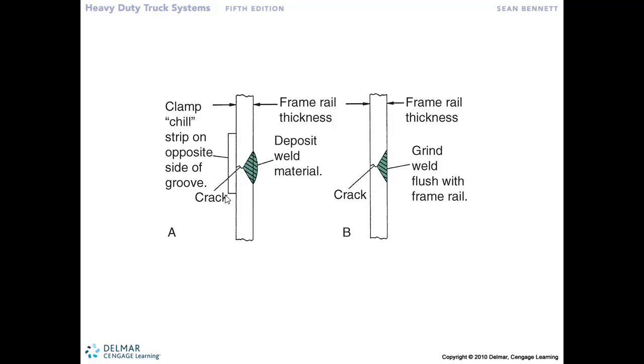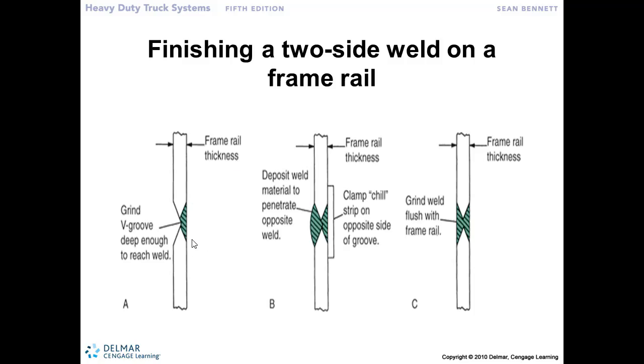We'll use a chill strip — a copper strip that helps extract heat out of the frame and dissipate it, aiding in the transfer of heat during welding. Once we've made the repair to one side of the crack, we go to the other side, grind it out, fill it with weld, and then grind it down to the original thickness. That way we've terminated the crack, ground it out, and filled it with good material from the weld.